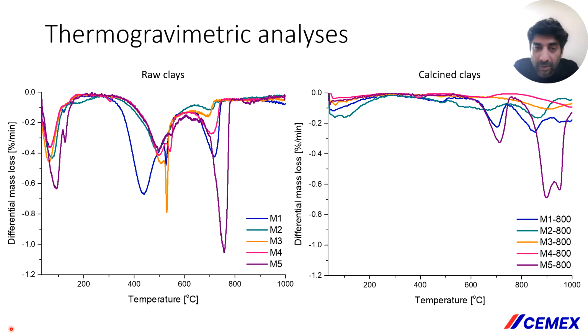One thing you'll pick up on is the intense mass loss observed between 800 degrees Celsius and 1000 degrees Celsius for clay M5, highlighted by the two peaks centered at 900 and 950. These appear to be new phases because no mass loss was previously observed in the raw clays at this temperature. A possible explanation could be the formation of an amorphous transition state between free lime and metakaolin, or possibly other formed aluminosilicates.